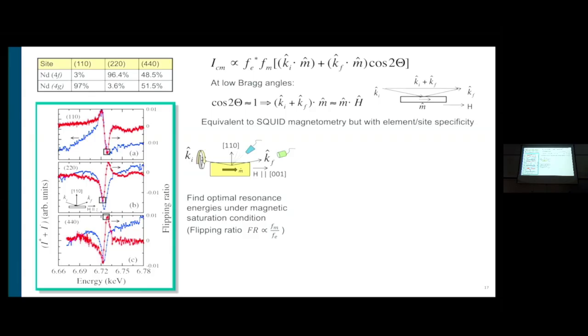And if you are at small Bragg angles where 2 theta is not large, cosine 2 theta is close to 1, Ki plus Kf is parallel to the magnetization and the applied magnetic field. So in a way, what you're measuring is the projection of the magnetic moment along the field. This is the same that you measure in squid magnetometry. It's just that you have element and site selectivity.